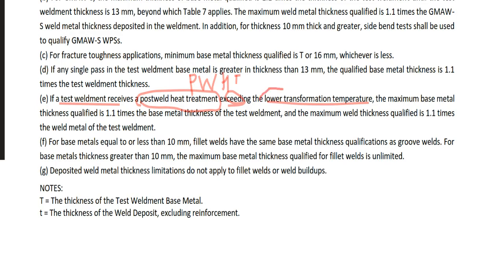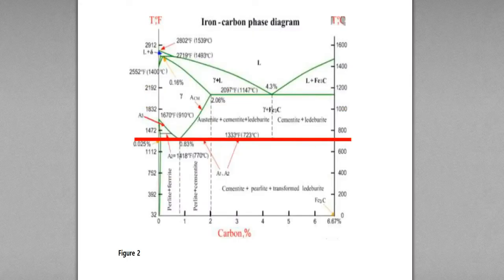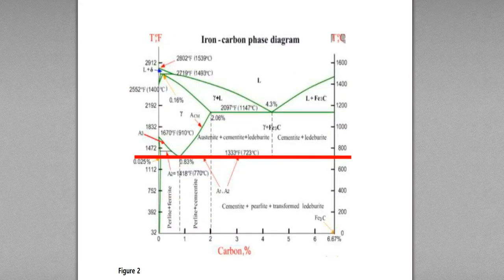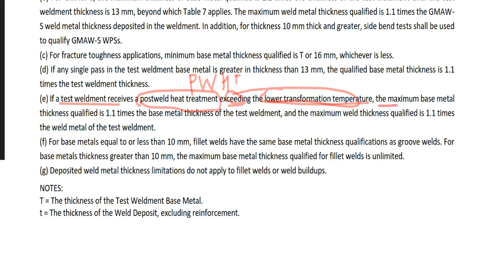And this lower transformation temperature is here. This is the iron carbon equilibrium phase diagram. And this red line here is the lower transformation temperature, which is 723 degrees Celsius. So PWHT over this lower transformation temperature, the maximum base metal thickness qualified is 1.1 times.